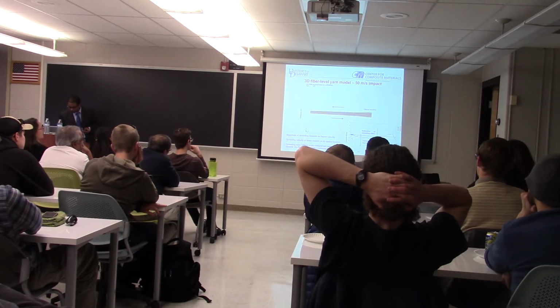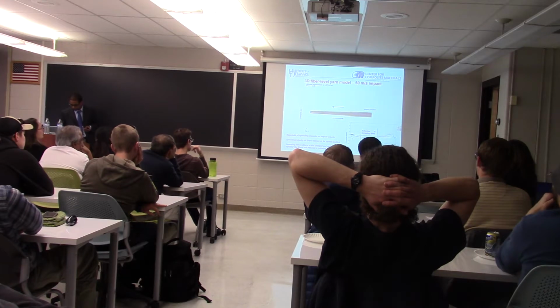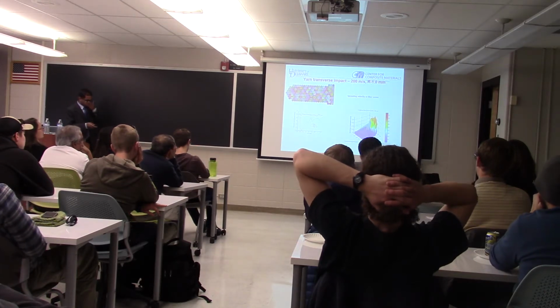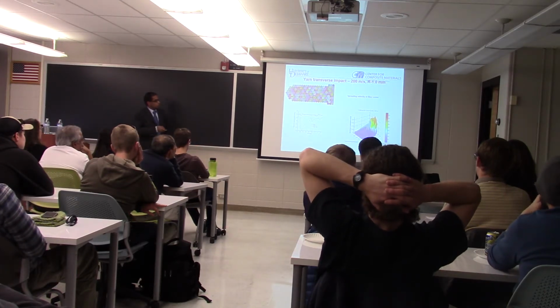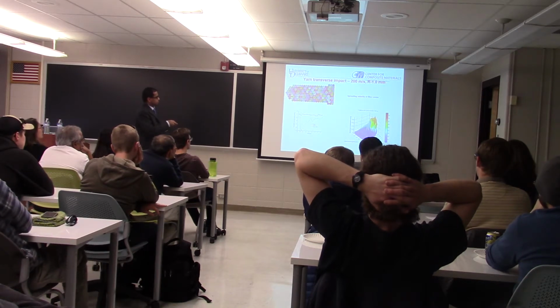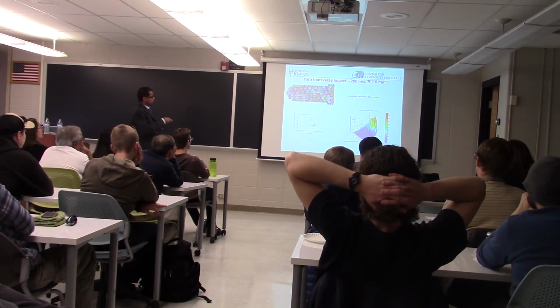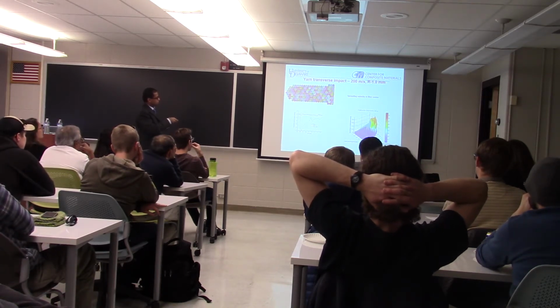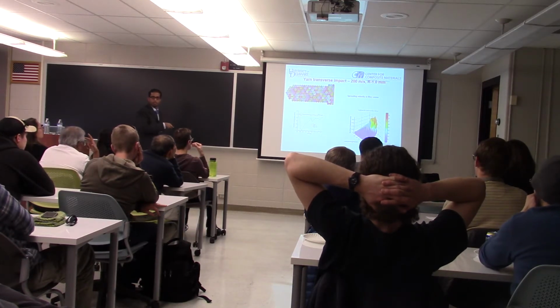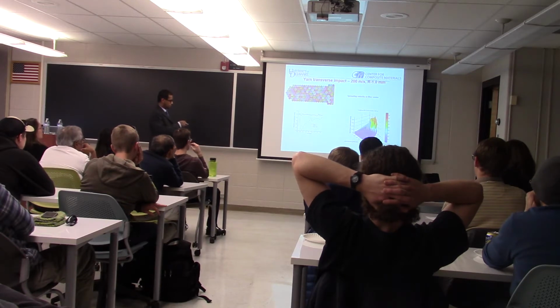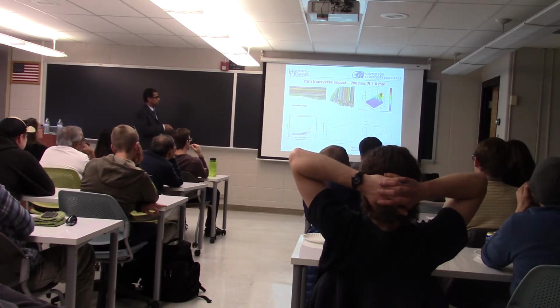So looking from top down, the spreading wave initiates from the impact location, it goes to the clamped end and then reflects and comes back. So there is a gradient in the spreading velocity for all these fibers. So the spreading velocity is maximum for the fiber on the outermost at the yarn width, because this fiber is unconstrained. It's free to move in this direction, so it's maximum at that location.